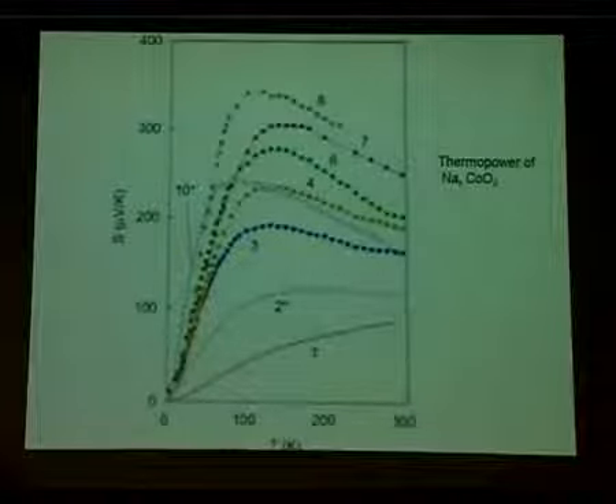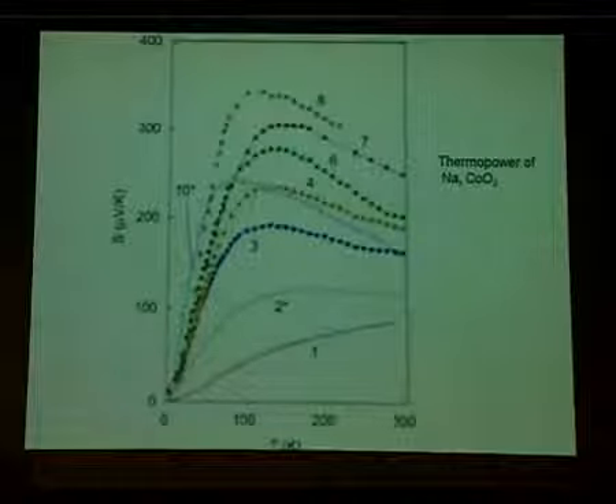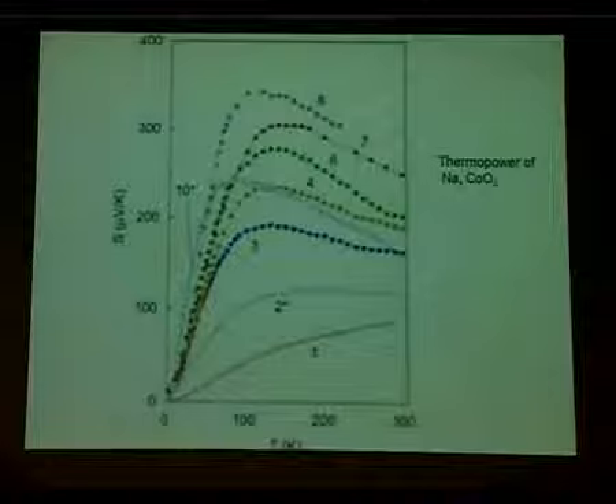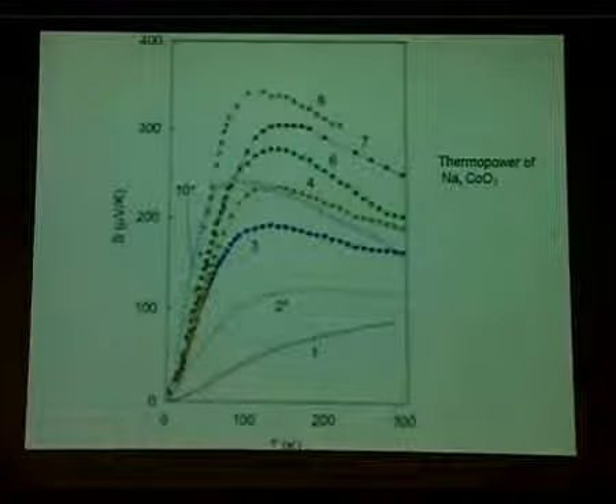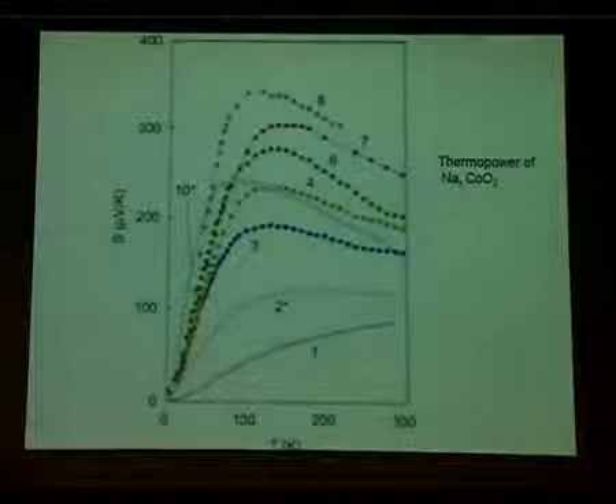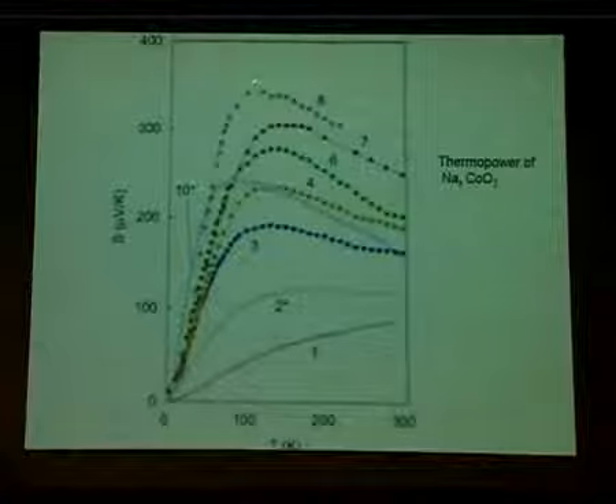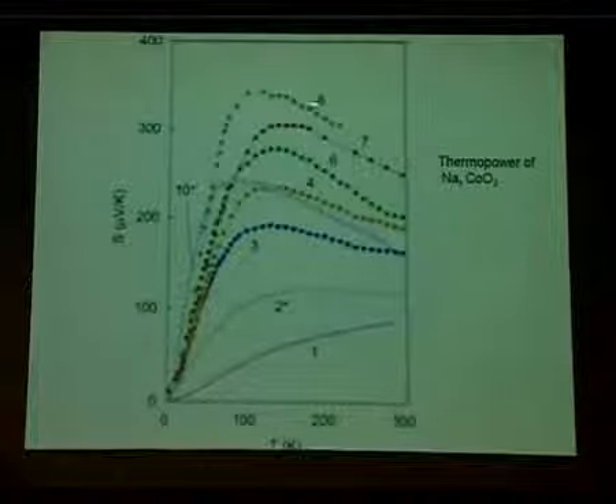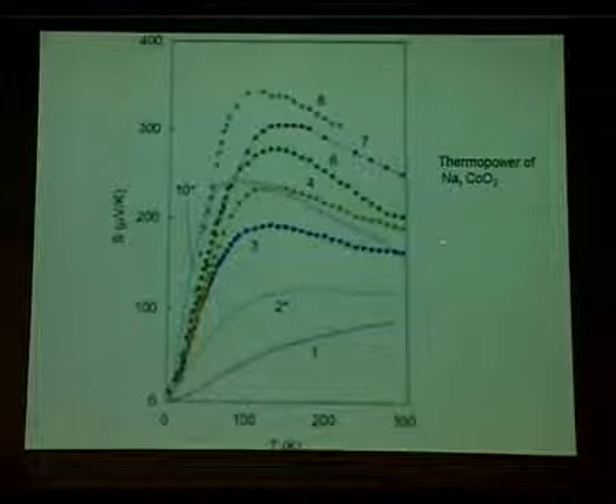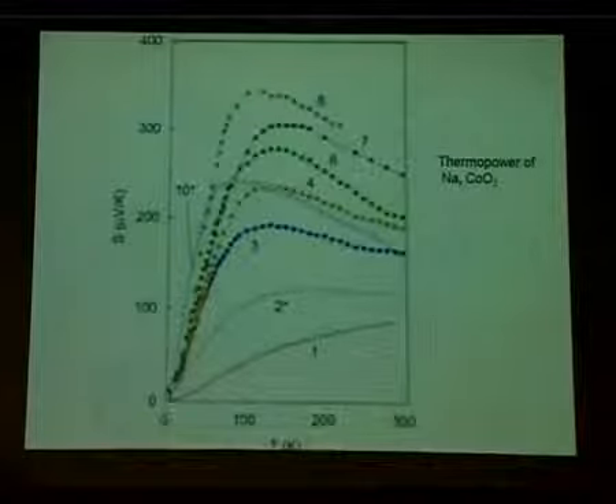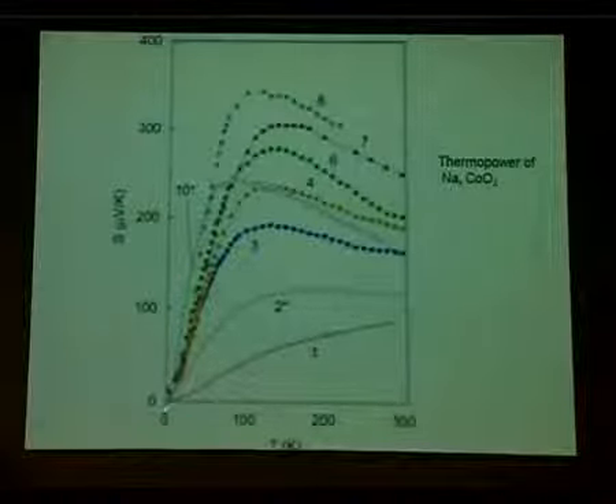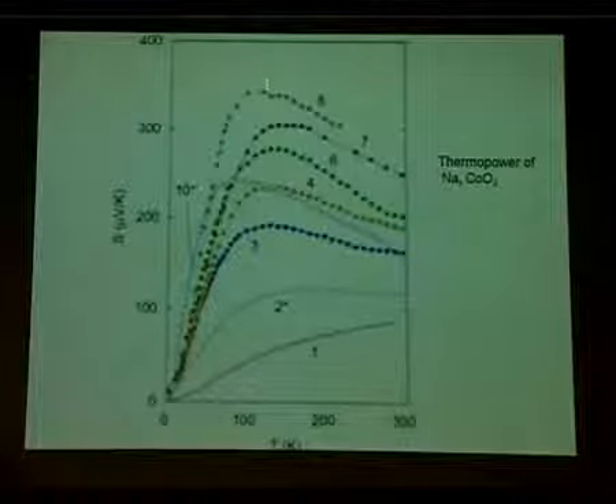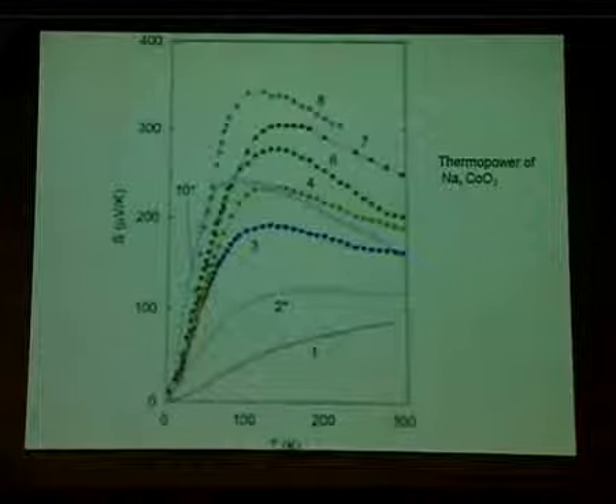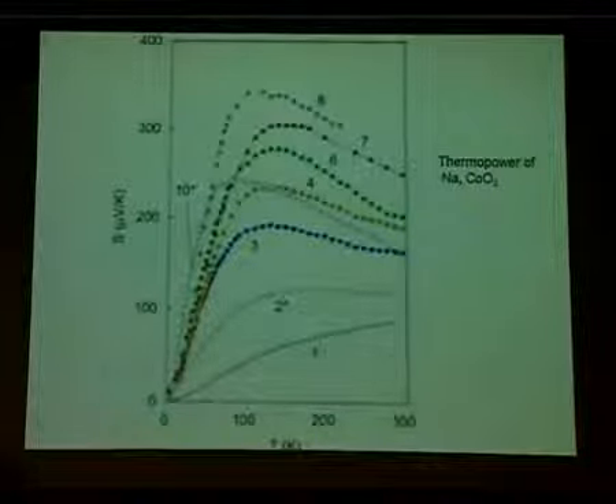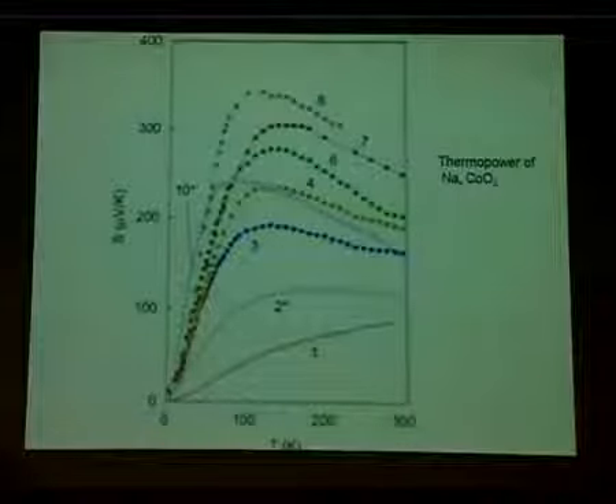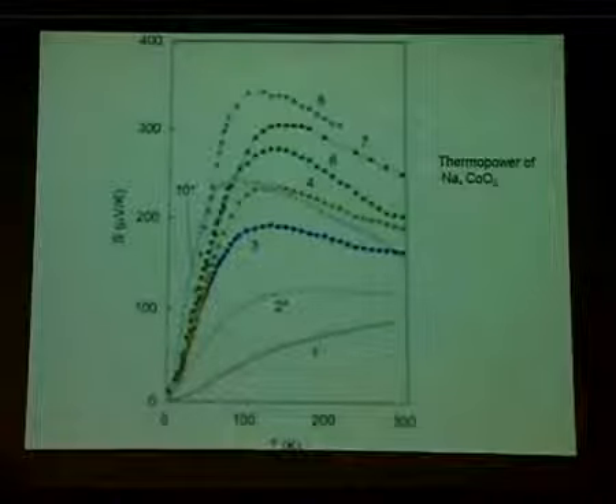But suppose it were a completely non-degenerate system. Electrons are like dots sitting there, and they are moving around and carrying electrical current. As they move, there is a flow of entropy, and so there is a thermopower. And if they are classical objects, there will be some number which will characterize the thermopower. So that is what is happening in these systems. It is as if it was a degenerate system, but the temperature at which it became non-degenerate is about 100 degrees or so. So above this very low temperature, it behaves as some kind of a classical or incoherent system.